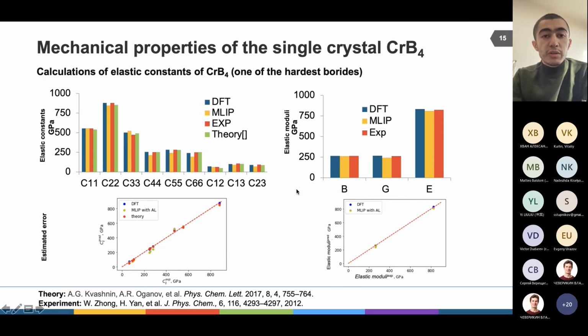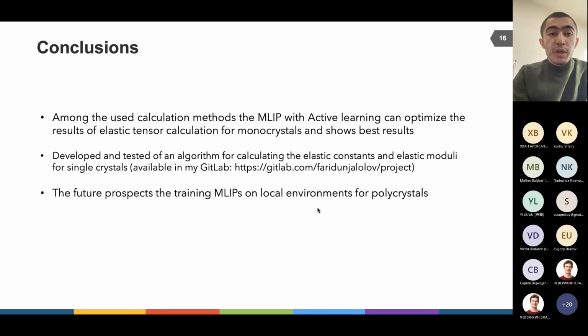And the last material is chromium tetraboride, one of the hardest borides. Here you can see the comparison of calculated DFT and machine learning interatomic potentials with experiment and with theoretical calculations from the literature. And also here machine learning interatomic potentials show results in good agreement with DFT and experiment. In conclusion, we can say that among the used calculation methods, the machine learning interatomic potentials with active learning can optimize our results of elastic tensor calculations and show the best results for monocrystals for now.